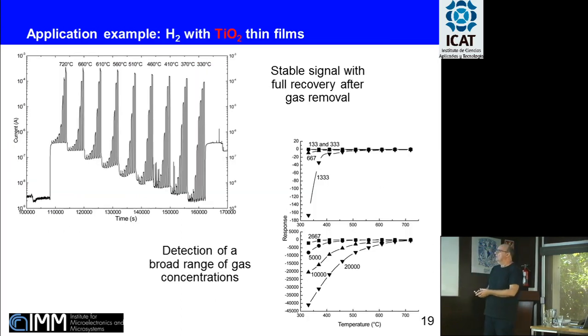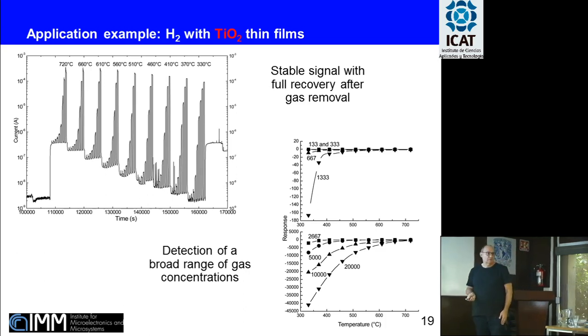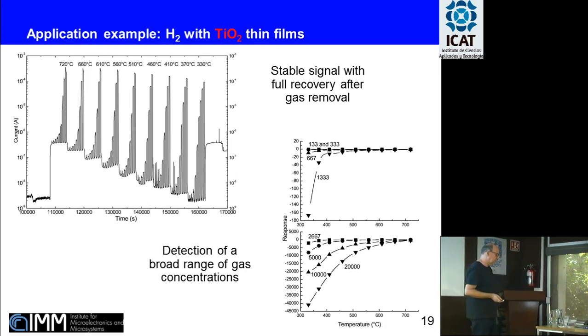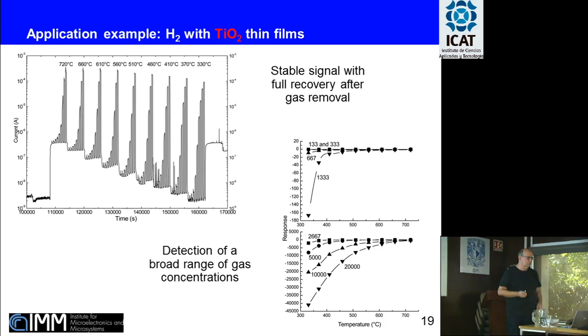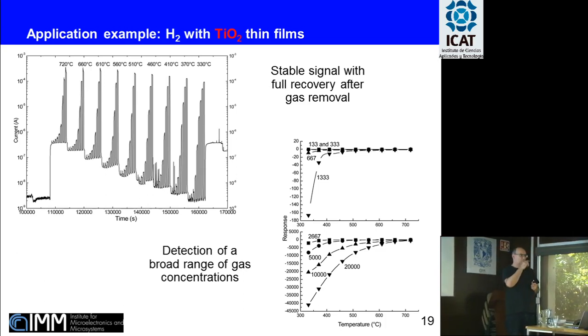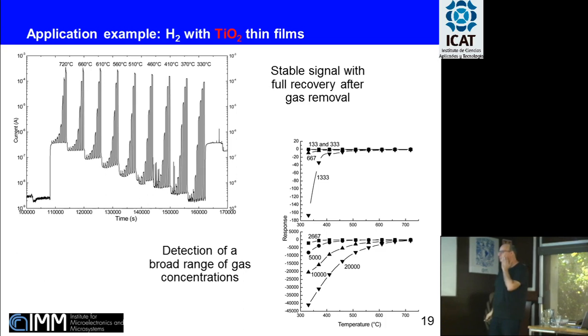Another example, hydrogen detection with titanium dioxide thin films, which showed similar results, a very interesting signal over a broad range of operating temperatures, over a broad range of hydrogen concentrations. These are the calibration curves. It's not so interesting to show dozens and dozens of results of gas sensing, just to show that the circle was closed from the very early conception of the precursor to the processing, device testing, and demonstration that the whole process could be closed. The whole circle, the whole loop could be closed.